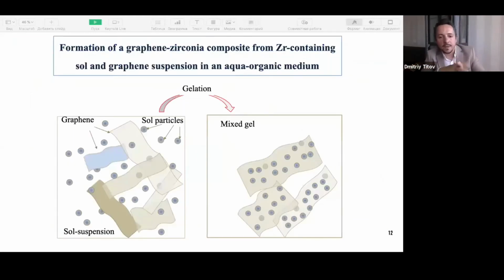So we think that the sol particles are isolated between the graphene sheets as nanoreactors, where the sol-gel transition occurs. The resulting gel is also bound to the graphene sheets. During the suspension calcination, the organic-inorganic complex is destroyed and crystallization takes place directly on the graphene. So graphene saves its unique electronic properties, and at the same time it is fixed in the composite structure.